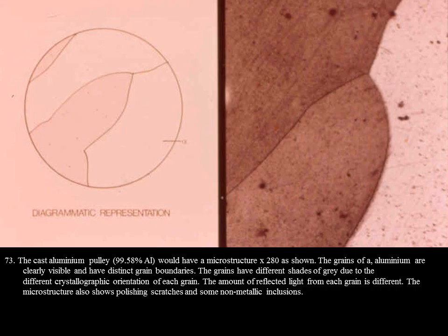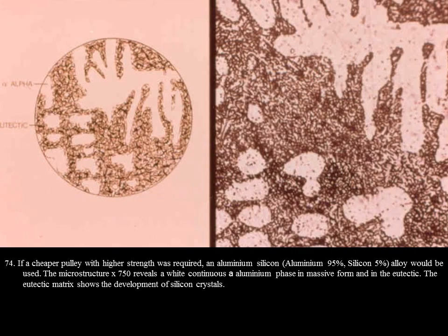The cast aluminium pulley of 99.58% aluminium would have a microstructure at 280 magnifications as shown. The grains of alpha aluminium are clearly visible and have distinctive grain boundaries. The grains have different shades of grey due to the different crystallographic orientation of each grain. The amount of reflected light from each grain is different. The microstructure also shows polishing scratches and some non-metallic inclusions.